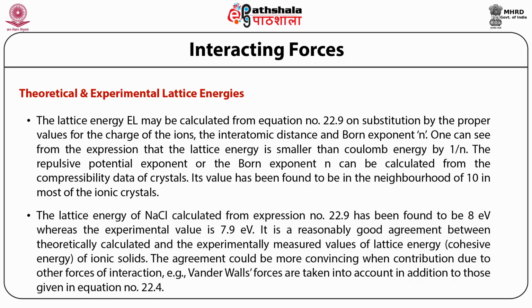The lattice energy of NaCl, calculated from equation number 22.9, has been found to be 8 electron volt, whereas the experimental value is 7.9 electron volt. It is a reasonably good agreement between theoretically calculated and the experimentally measured values of lattice energy, which is also known as cohesive energy of ionic solids. The agreement could be more convincing when contribution due to other forces of interaction, that is van der Waals forces, are taken into account in addition to those given in equation number 22.4.